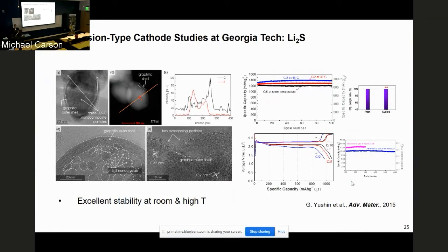And typically, conversion materials degrade much faster, especially if you go to elevated temperatures. They typically exhibit much larger voltage hysteresis or energy losses during charge and discharge. And they demonstrated that, yes, all this degradation can be overcome, it can be dramatically reduced. You can have very stable performance for hundreds of cycles, in this case 600 cycles, demonstrated at Georgia Tech, and again have very small voltage hysteresis during charge and discharge.